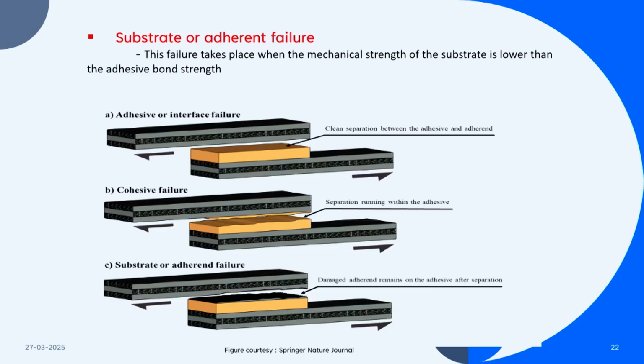Bond line thickness and uniformity of the bonding layer also matter. Sometimes it is applied using brushing or something similar, so how uniformly you can coat the adhesive on the substrate surface plays a crucial role. Another cause of cohesive failure is that the adhesive does not have enough strength and is too soft. Pores can also lead to cohesive failure. Substrate or adherent failure occurs when the mechanical strength of the substrate is lower than the adhesive bond strength. That clearly tells you this adhesive system is not suitable for that substrate, so you have to change the adhesive or change the substrate.